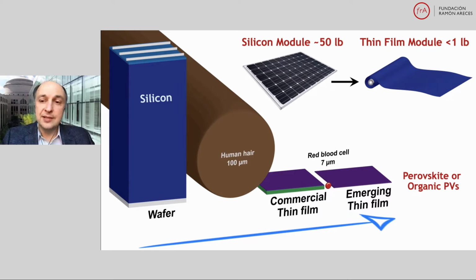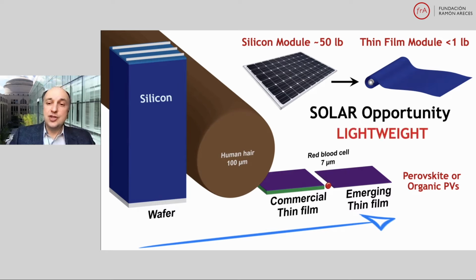If instead we use nanostructured films, we can make them into thin, flexible rolls of material, and they would weigh significantly less than a silicon panel, maybe only 0.5 kilo for that same area of 1 by 2 meters in size. This gives us an opportunity to recognize that generating lightweight solar cells could be the new transformational technology to transform solar. How do we make them?